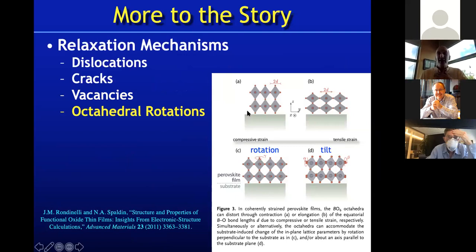Now, I've spent a long time talking about the biaxial compression, and I had a simple cartoon picture that looked like this, and biaxial tension, and I had a simple cartoon picture that looked like that, where all we thought about was uniformly distorting that octahedron. But as, again, Professor George talked about last week, the reality of the situation, particularly with perovskites grown in the 1,0,0 direction, is that these octahedra can do more than simply uniformly compress together biaxially or extend together biaxially. They can rotate.